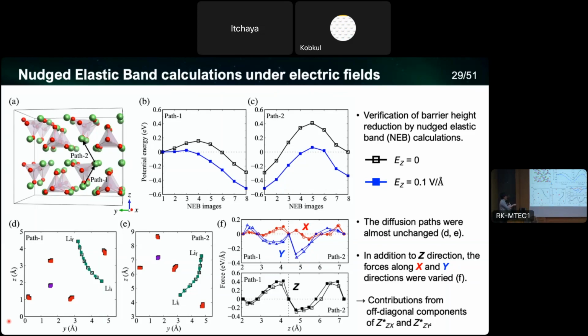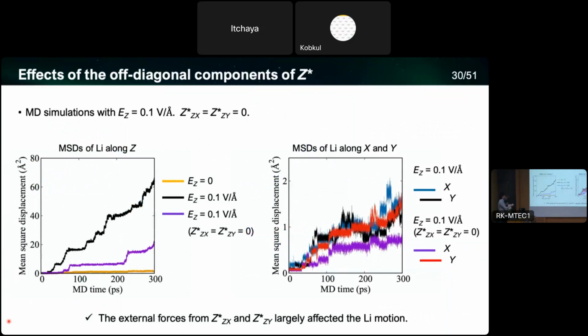And if you look at the lithium migration path, we cannot see obvious differences with or without electric field. But if you look at the forces acting on ions, there is a non-negligible difference. Of course we have differences along the z direction, which is the electric field direction. But we also have differences in the x and y directions. So we want to know the effect of these directions perpendicular to the electric field, which actually comes from the off-diagonal components of the Born effective charges. Then here is another molecular dynamics simulation to see the effect of the off-diagonal components.